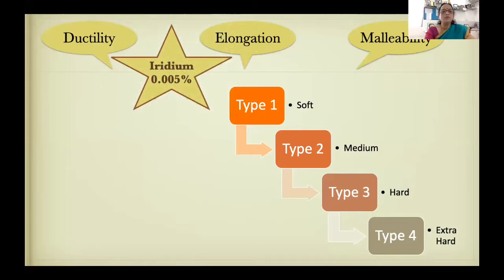Now, addition of a small amount of iridium in these alloys can improve the ductility of some hard alloys. As I said, as the gold content reduces, the ductility and malleability of the gold is lost. So type 2 is not as malleable as type 1. So when we want to increase the ductility or elongation percentage of these, a very small amount of iridium or even ruthenium is added, up to a percentage of 0.005%, which will act as grain refiners because of their high melting point. And these will actually help in increasing the malleability of type 2 and type 3 hard alloys.